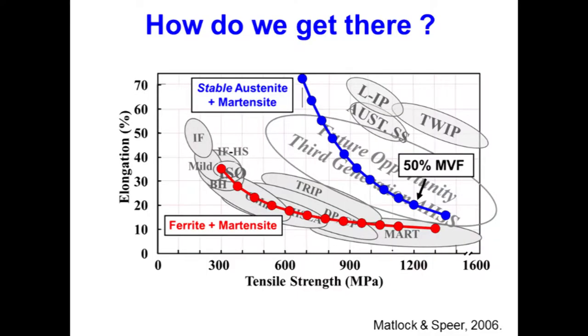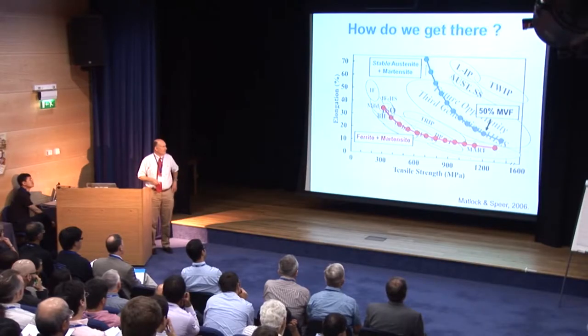This is a simple model developed by my colleague David Matlock, really looking at composite models for predicting uniform ductility based on phase properties. And you can see if we look at combinations of ferrite and martensite, we get property combinations that you would expect that are fairly parallel to the different grades on the banana diagram, so ferrite-based steels.